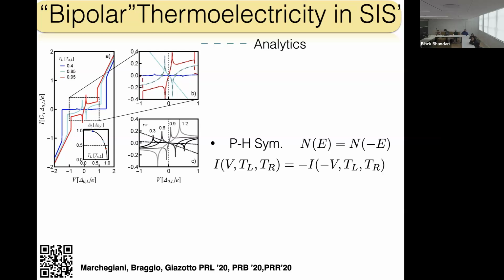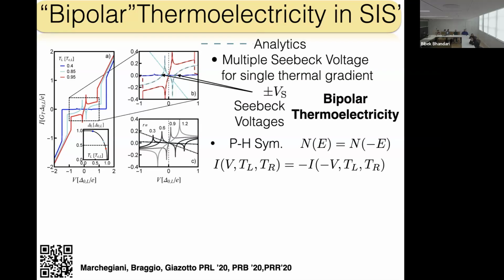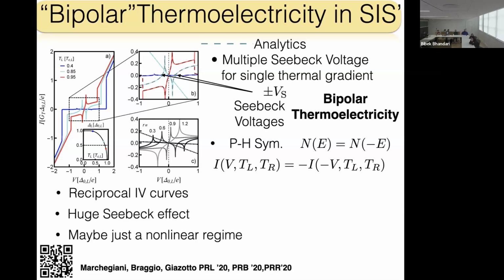And here you see also another important point. I'm changing the temperature of the hot lead, and this is hotter than this. But you see that this is dissipative, and this becomes thermoelectric. So essentially you see here the nonlinearity of the problem. Because in a certain sense, you are increasing the gradient, and at a certain point the thermoelectric effect disappears. Okay, so things are weird. But for me, the most striking point is exactly the bipolar thermoelectric effect, and if you compute the Seebeck effect, the nonlinear Seebeck coefficient, it's really huge.